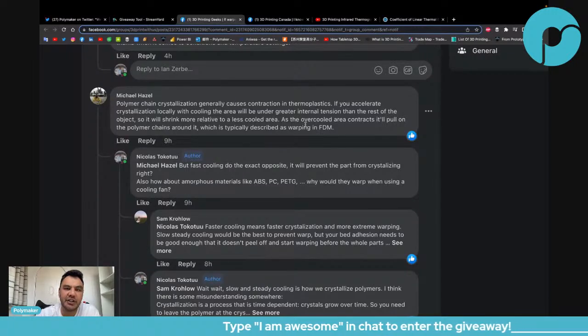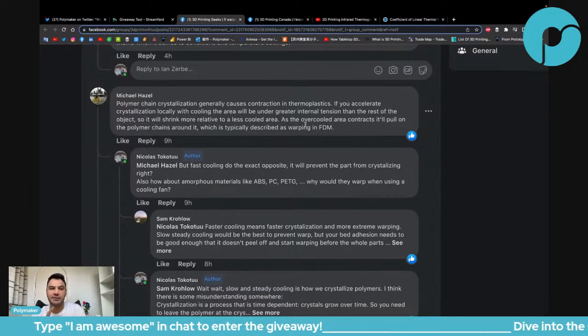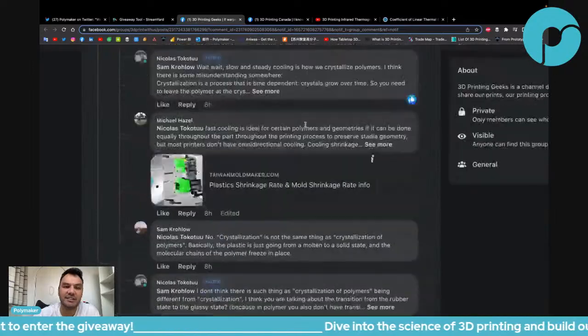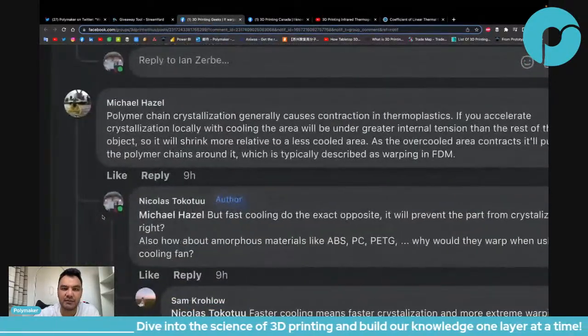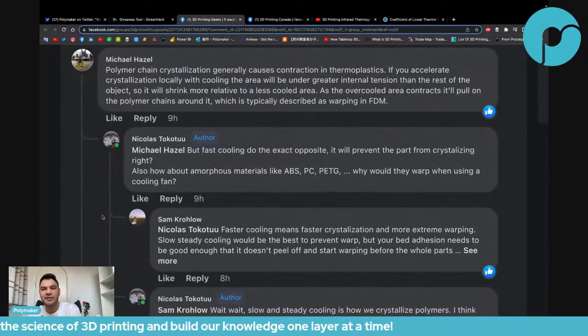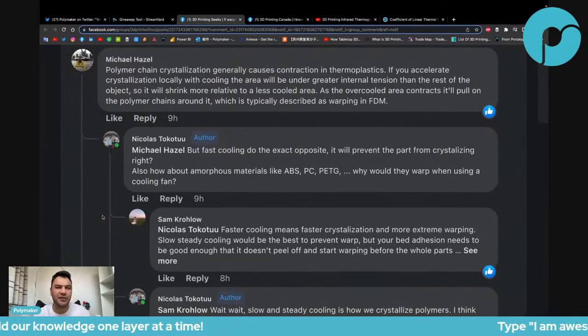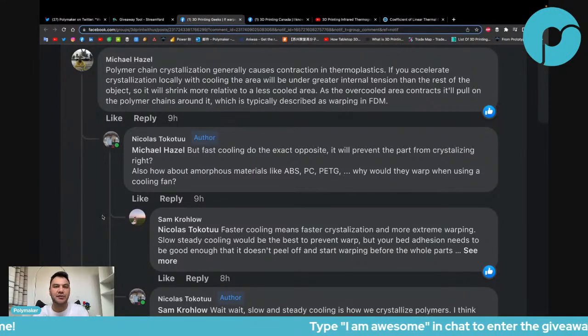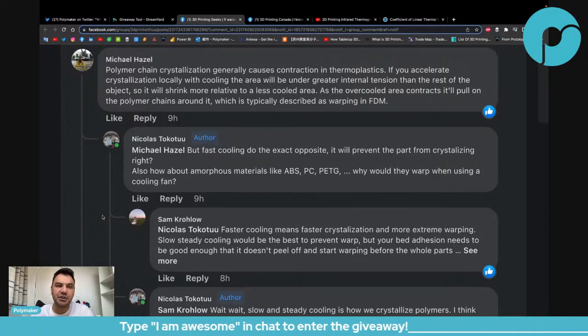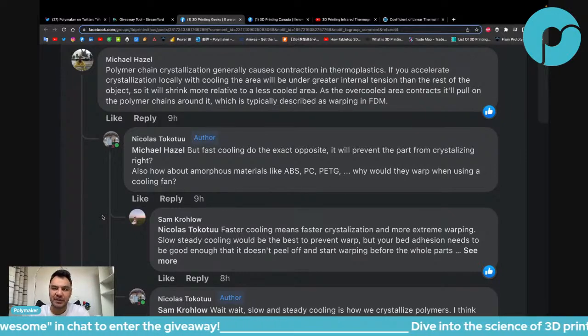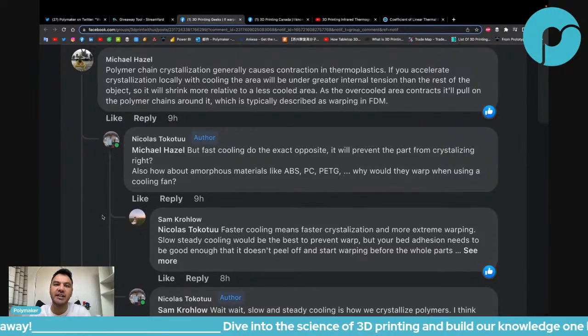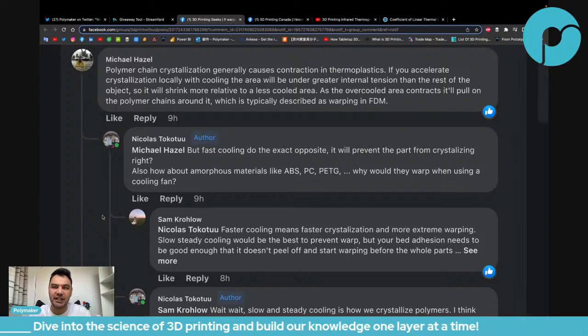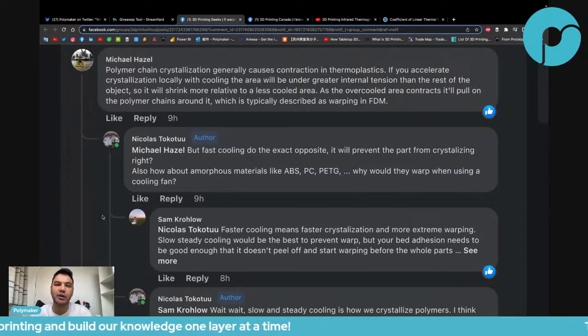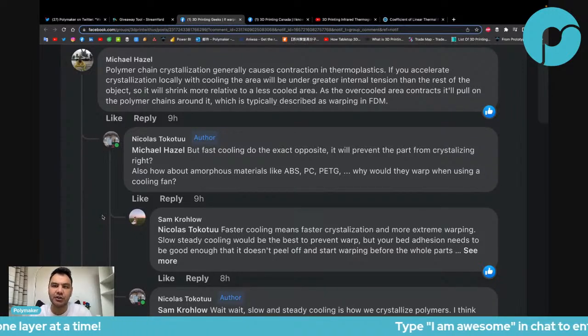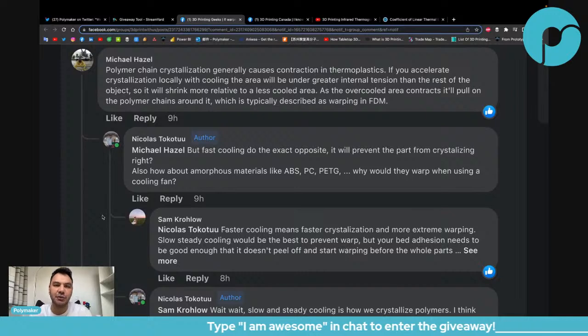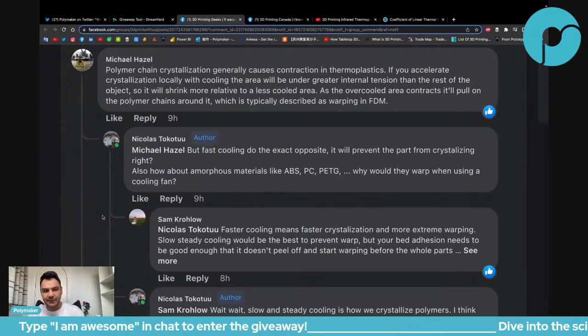Polymer chain crystallization generally causes contraction in thermoplastic. Oh, I remember that. Okay, so check this properly. When some people talk about polymer stuff and other people are reading, if it's not very true, that brings a lot of wrong information. So check this: polymer chain crystallization generally causes contraction in thermoplastic. If you accelerate crystallization locally with cooling, the area will be under greater internal tension than the rest of the object, so it will shrink more relative to a less cooled area. As the overcooled area contracts, it will pull on the polymer chain around it, which is typically described as warping in FDM.